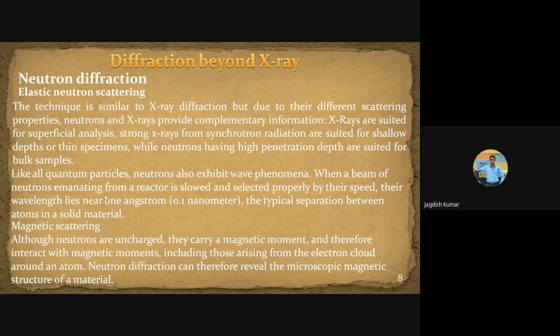In a typical antiferromagnetic crystal, you may have one atom with the upspin, then a neighboring atom with the downspin, then a third atom with upspin, and a fourth atom with the downspin, and so on. So you have upspin planes with an interplanar spacing double the interatomic spacing. Means in a typical simple antiferromagnetic arrangement, you will have magnetic planes which have the interplanar spacing double the interatomic spacing. So you will be seeing additional peaks because of those planes.